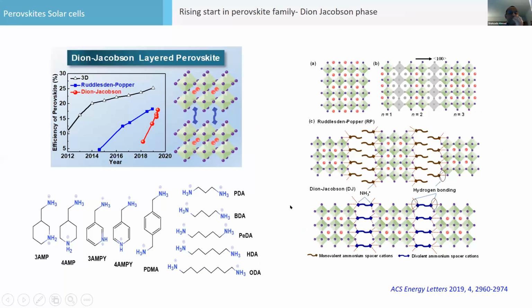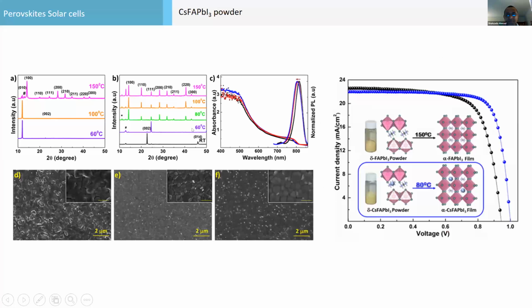There's another two-dimensional perovskite, the Dion-Jacobson. Before it was the RP phase, and Dion-Jacobson is another very good perovskite here in the layered perovskite category. By placing different organic groups here, you have plenty of opportunity to design new types of DJ phase perovskite. And this efficiency, in the red curve you can see, is also increasing to 18%. These are much more stable perovskites than the three-dimensional perovskite.